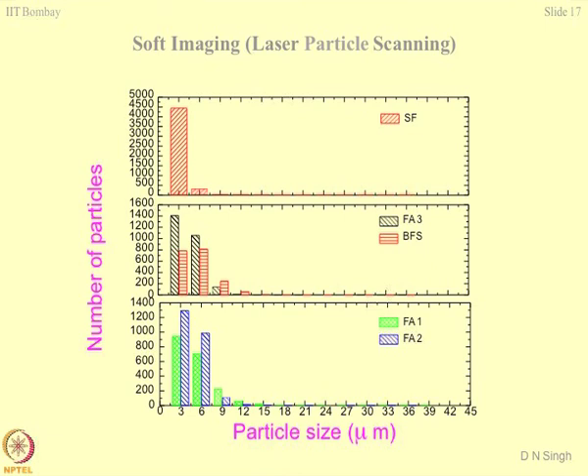You will notice that if you do the analysis for silica fume, the question comes: why should we do this analysis for silica fumes? Can't you find out particle size distribution by some other method? No — first of all, they are all sub-micron particles and they are much lighter than air, so even if you make a slurry of it nothing will settle down, so a hydrometer cannot be done. For sieving, there are lot of losses and nothing will pass through the sieves. In this situation, soft imaging analysis becomes the best option where you can magnify the grains and see their shape and count the size.